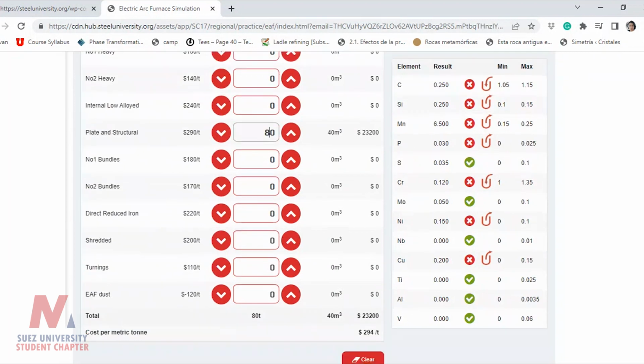But the problem here is the residual content related to molybdenum, nickel, niobium, copper, titanium. Titanium no, because you have zero actually, but copper, niobium, nickel, molybdenum. If you have a higher percent than the maximum, you can reduce none of these elements when you are melting. That's some of what the classmates mentioned last time.